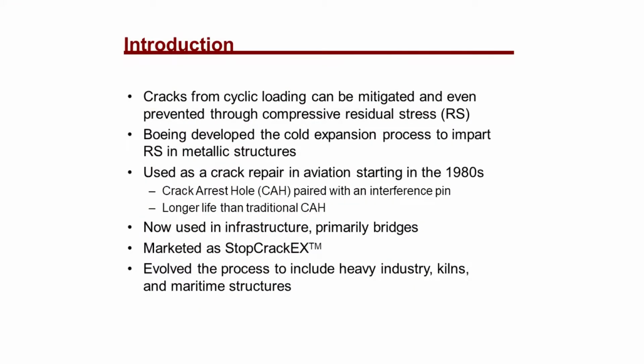So it's been used as a crack repair in aviation, which may seem a little strange that you have a hole as a stress riser, but it can also be used as a crack mitigator. And that's because when you drill that hole in front of the crack, you are giving that crack tip a larger radius to distribute the stress intensity factor. So it does work for a little while. But as you're going to see here shortly, it's not a long-term fix.